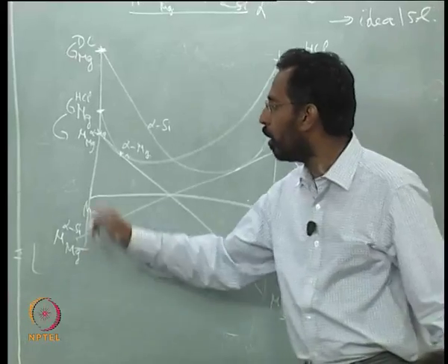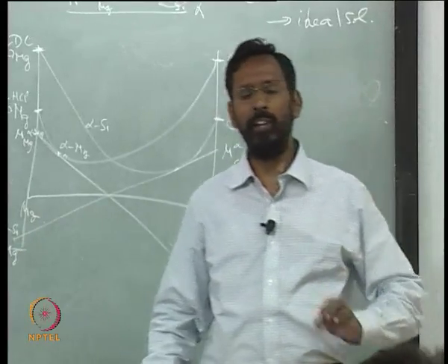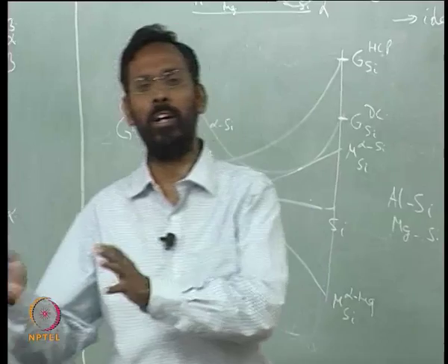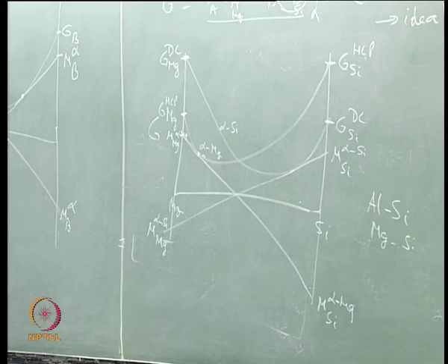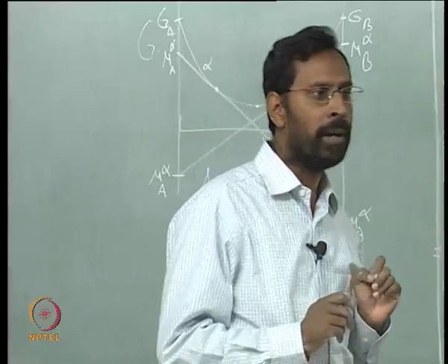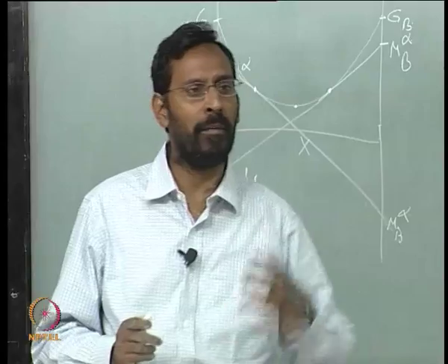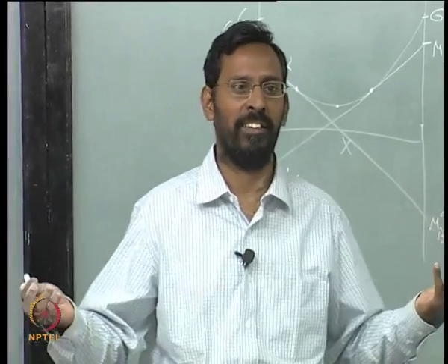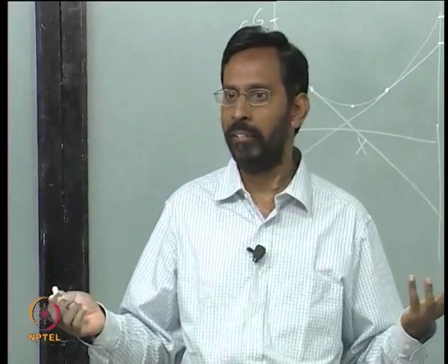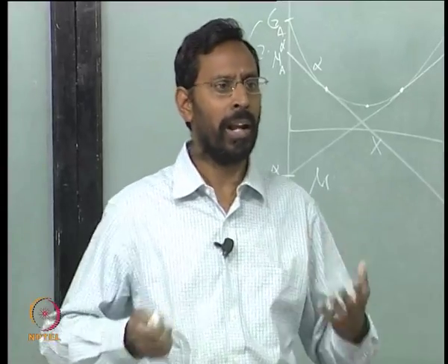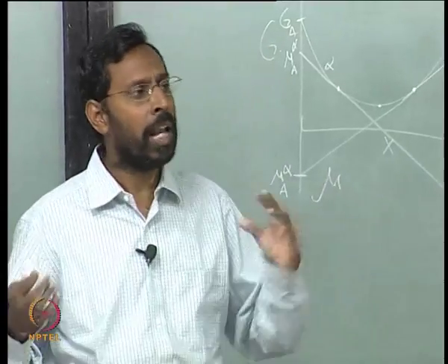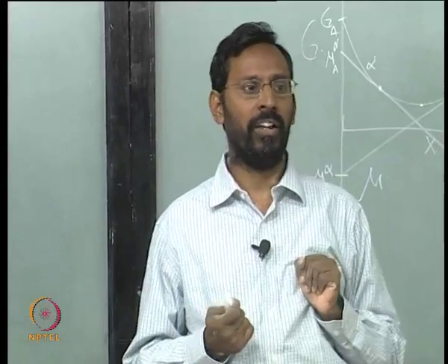So, always remember, we cannot say this is the chemical potential of a particular phase, we always say this is the chemical potential of a particular element. Chemical potential is always for a given element, activity is always for a given element, activity is never for a phase. We talk about activity of elements. Similarly, chemical potentials of elements, and in which phase, that is what we look at.